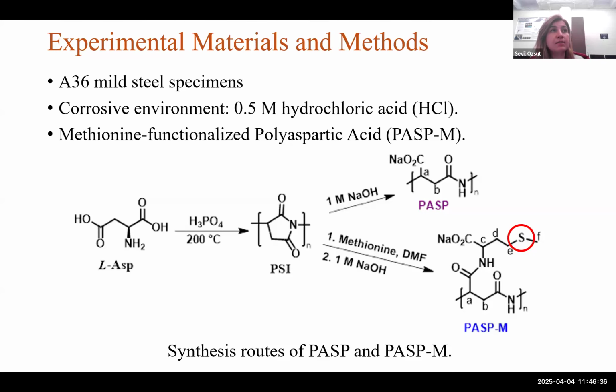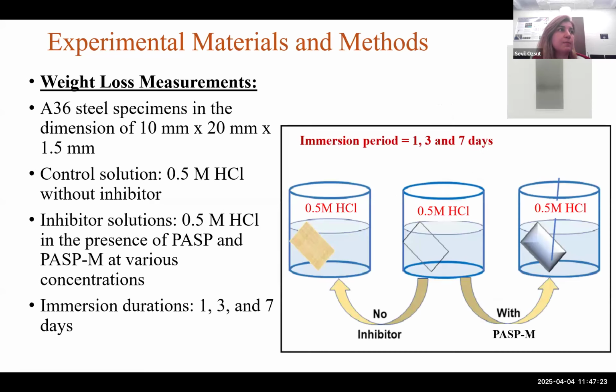Moreover, they have some properties common to biopolymers derived from microorganisms, plants, and other sources. It's a totally biodegradable and non-toxic material. And we selected methionine, again an amino acid, which contains a sulfur atom in its structure, because based on my previous analysis and according to the literature, heteroatoms like nitrogen, oxygen, and sulfur provide more adsorption sites and good corrosion inhibition for the inhibitors.